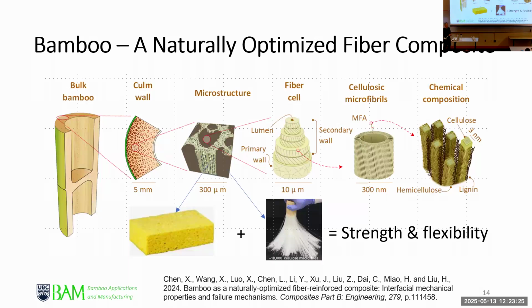But in layman's terms, when it comes to properties, we consider bamboo as a naturally optimized composite material, where you got the soft tissues, parenchyma cells acting like a sponge. And then you got the continuous fiber. This is actually real. Somebody did a study at the University of Maryland, and he actually dissolved the bamboo by removing all the lignin and hemicellulose and was able to get continuous macrofiber. You cannot do that with wood without dissolving the whole thing. So that just shows that bamboo fiber is really straight and well connected. And that continuous fiber plus the soft matrix makes bamboo strong, but also flexible.